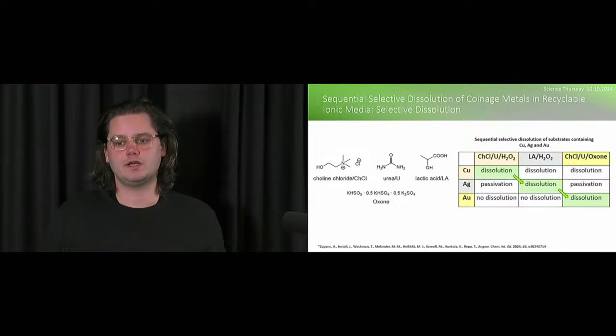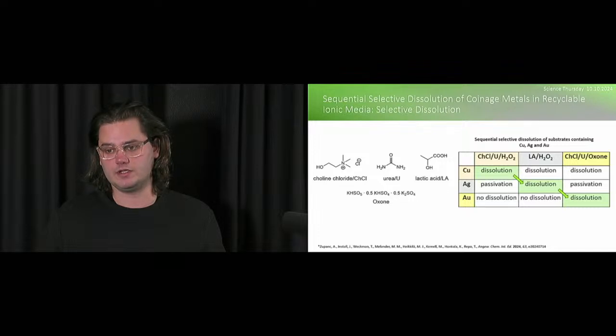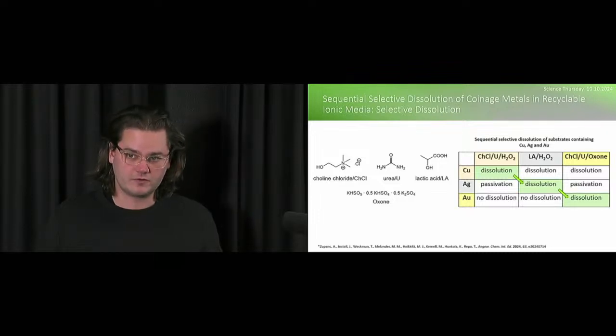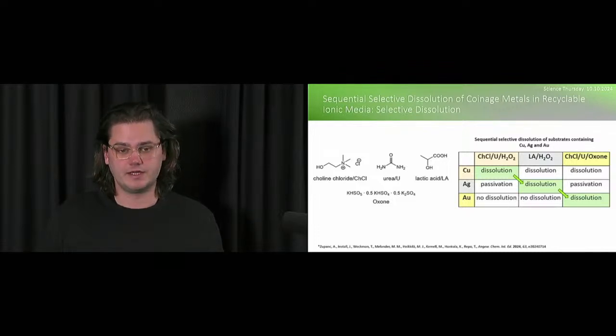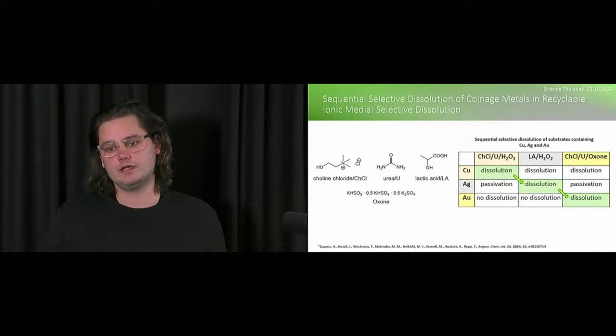What we managed to do was, using the proper oxidant, we were able to dissolve each metal separately from the other 2. So we had conditions with choline chloride urea using hydrogen peroxide as an oxidant, where we could dissolve copper, but we couldn't dissolve silver and gold. So we had the first selectivity. But if we switched from hydrogen peroxide to oxone, you can check the far right part of the table there. So the choline chloride urea oxone system can dissolve both copper and gold. But if we already dissolved the copper before with hydrogen peroxide in this media, we could have already here a selectivity to dissolve gold. So then we only needed to find some conditions where we could actually dissolve silver.